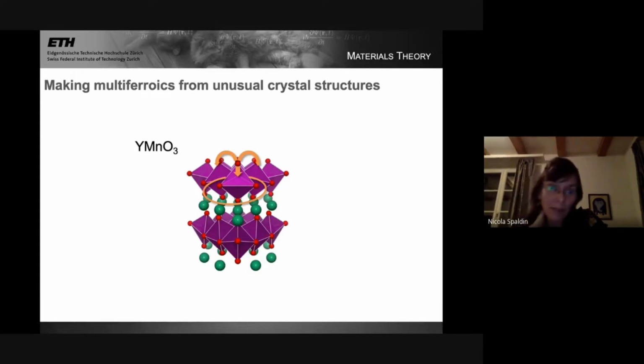Another approach that we took to making multiferroics was by basically using very unusual crystal structures. The example material that I'll discuss in a bit more detail, in which we use this angle, is called yttrium manganite. Just looking at the chemical formula, you might expect its structure to be very similar to bismuth ferrite. It has these 2 cations and then 3 oxygens, but it has this rather unusual structure, and I should point out, none of the ions here tend to be ferroelectric. So this is not a conventional ferroelectric, but it has this unusual crystal structure in which it has planes of triangular yttrium ions separating planes of corner-shared manganese-oxygen trigonal bipyramids.